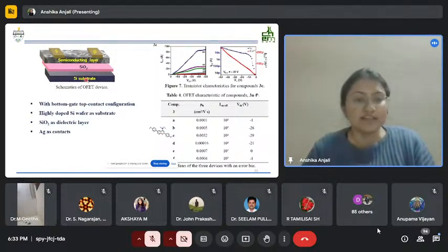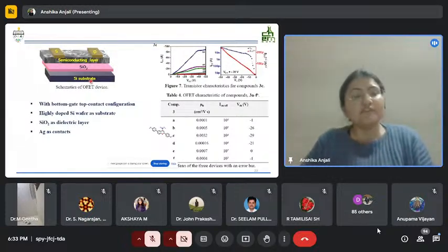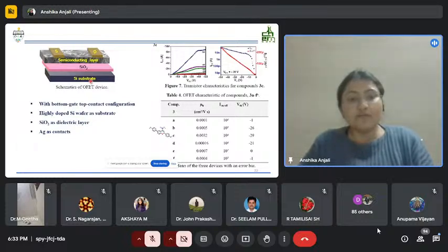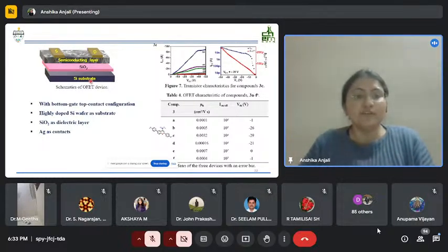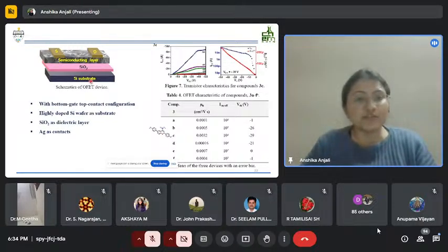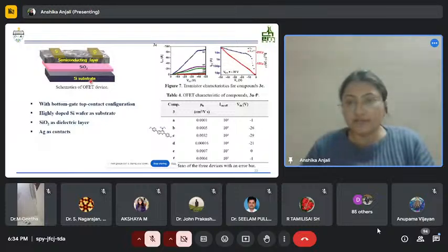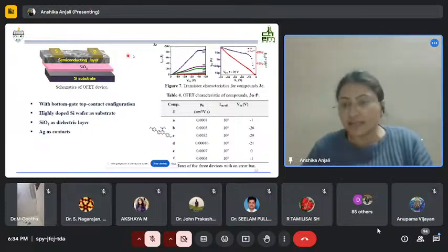We have used silicon wafer as our substrate. Then we have thermally grown silicon dioxide as our dielectric layer. Then we have spin coated our active layers using a spin coater with a static spin coating technique. And then we were having the source and drain terminals. Here, their transistor curves were plotted, and this is the characteristic transistor curve for compound 3C.